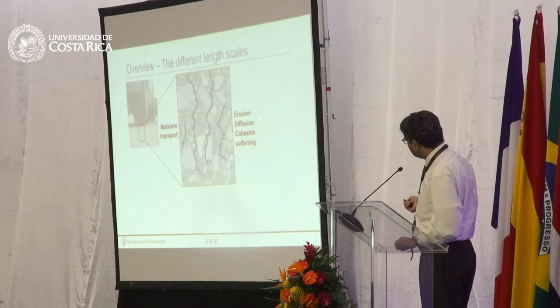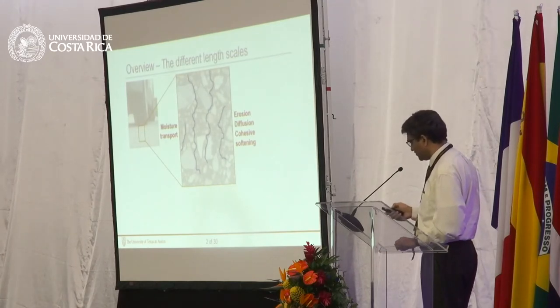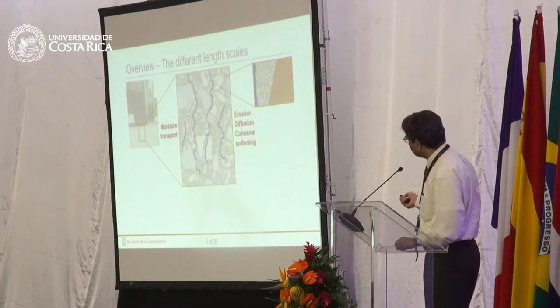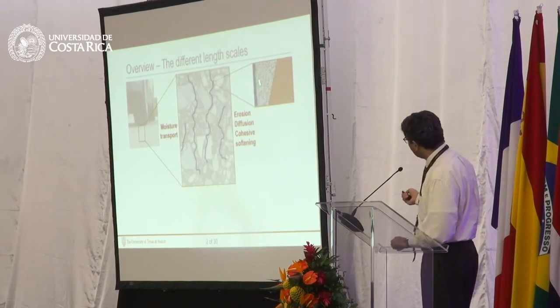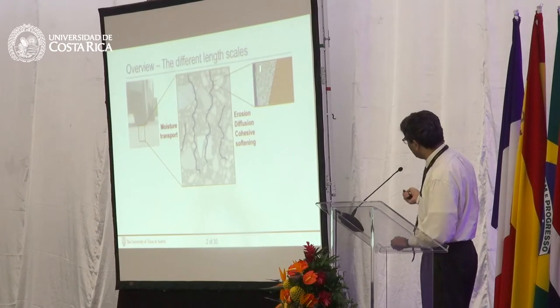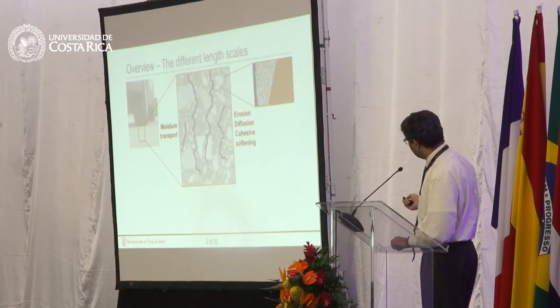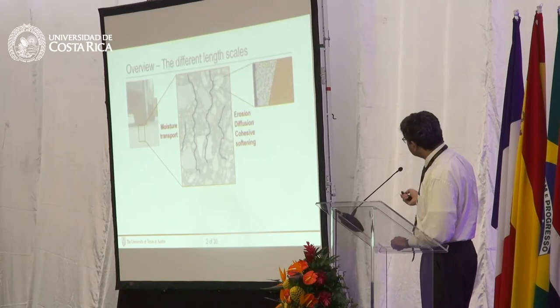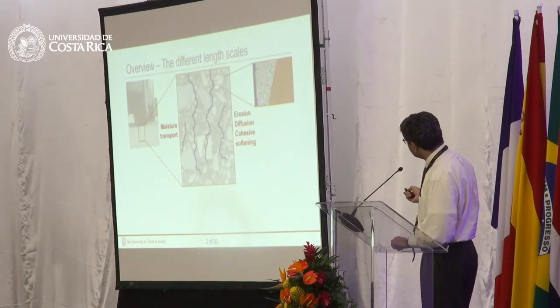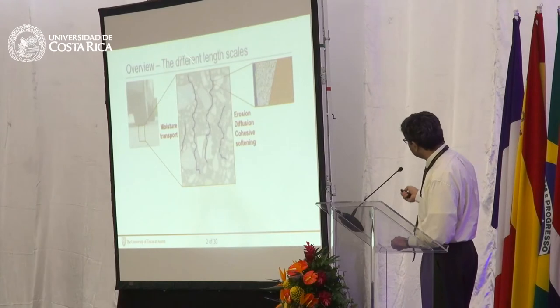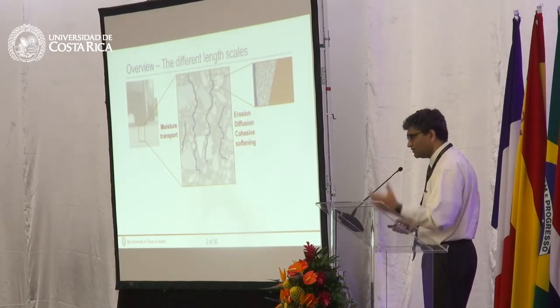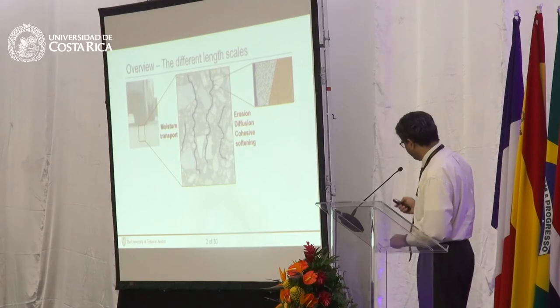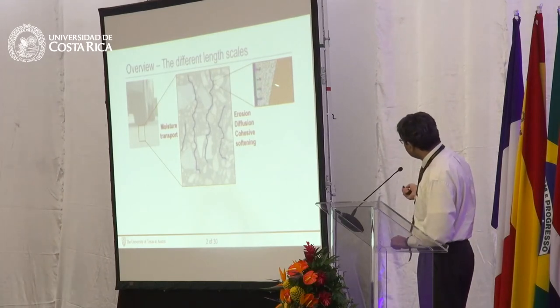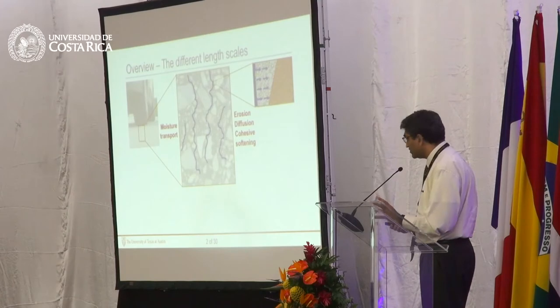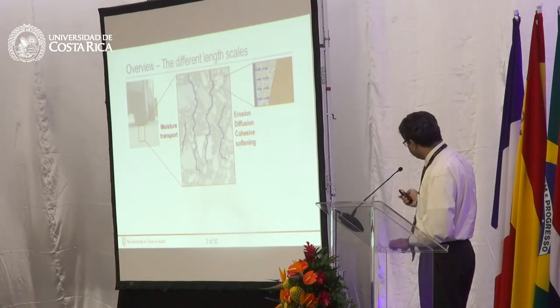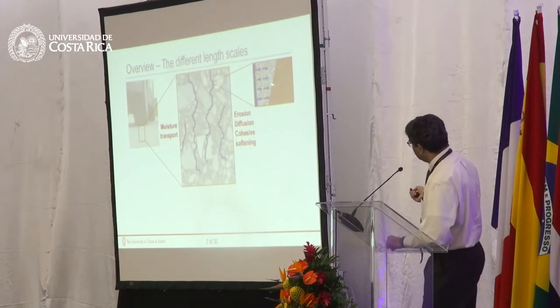You can have erosion, diffusion, cohesive softening, and so forth. If you think about it, here is a schematic that shows a small air void or a capillary right next to the mortar, right next to the coarse aggregate particle. When you start the process, you can have vehicle loads that create a pumping action that causes this water to flow in and out of that capillary, causing some kind of erosion. Simultaneously, water is also diffusing and making its way through the mortar all the way to the coarse aggregate particle. This part of the story we call diffusion.